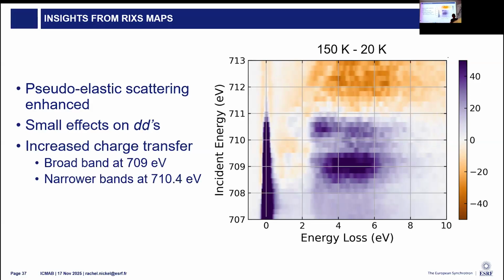Where we do see changes are the increased charge transfer as a very broad band at 709 eV and 2 narrower bands that show up at 710.4 eV. Finally, we have reduced fluorescence, which means that the ties between the atomic core levels and the conduction valence band is reduced at higher temperatures compared to lower temperatures. This could be a sign of some sort of metal insulator transition and probably points to the need of some sort of transport measurements on this system. But the 2 that I'm going to focus on are the bands that are showing up on the charge transfer, because we would like to be able to relate this change back to what site is actually causing it.